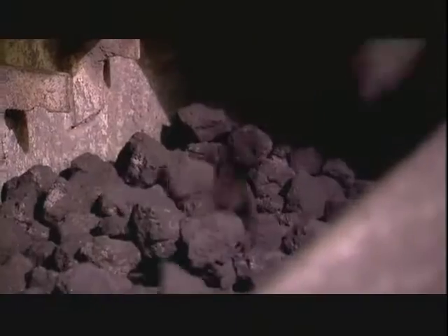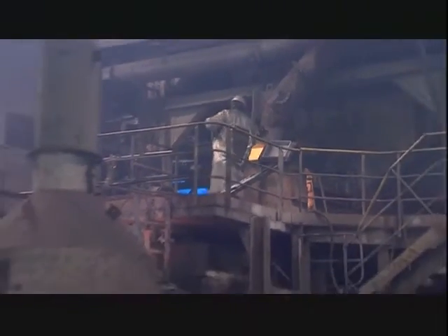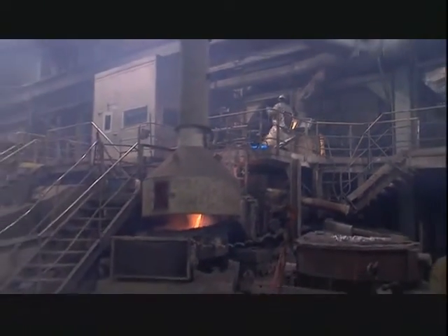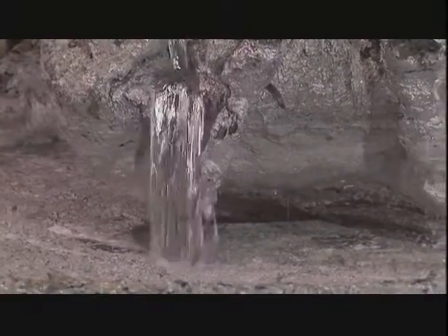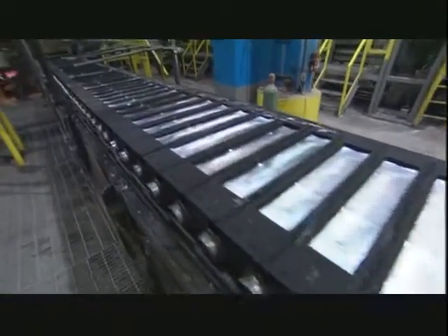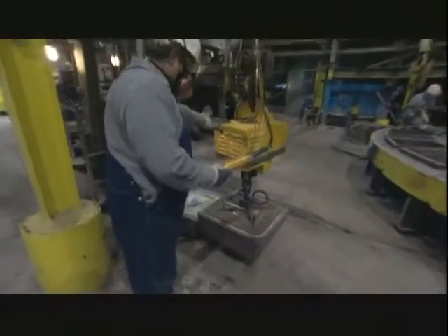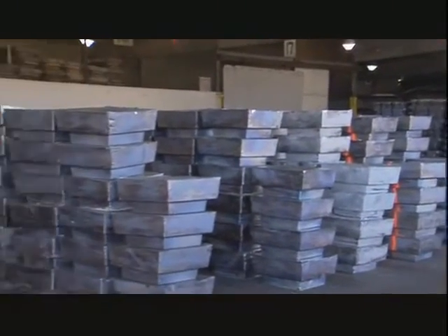The lead oxide moves to another furnace, where a mixture of carbon and oxygen generates a molten heat, 2500 degrees. This creates proper conditions to convert the lead oxide to metallic lead. After the refinements, the lead is now 99.99% pure. Molded into ingots weighing 60 pounds, 100 pounds, or 1 ton. Each year, a whopping 150,000 tons or more of lead emerges from Doe Run's refinery.